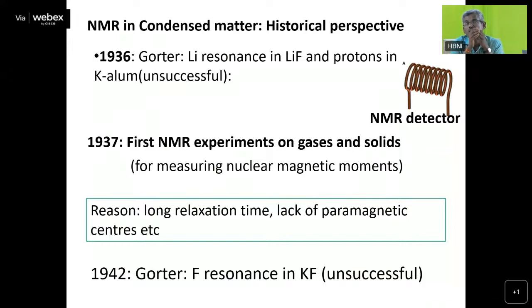The reason, which he was not aware of, was that there was no relaxation; nuclei like lithium and protons were not relaxing. If it is not relaxing, the signal gets saturated and you cannot detect the change in magnetization, because in NMR what we use is a coil. Coil is only the detector. If you take a solid state NMR probe and see, you will see only one coil. This coil is used to see the change in magnetization by applying a pulse or a carrier wave. So if there is no change in magnetization, you will not see a change in current. A coil will not detect a change in current and you will not get any signals.